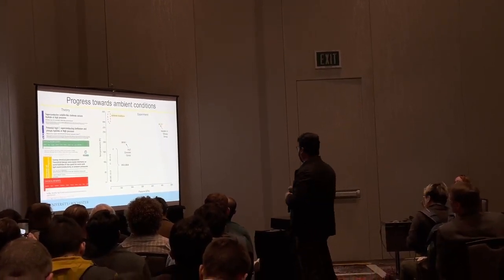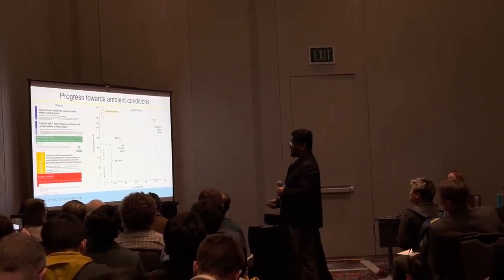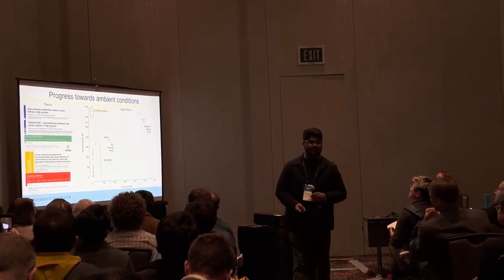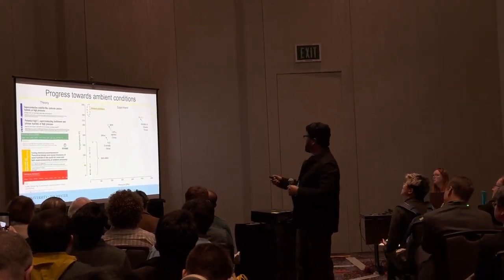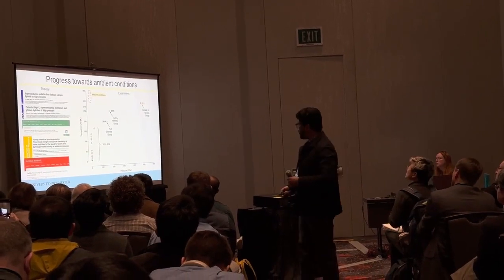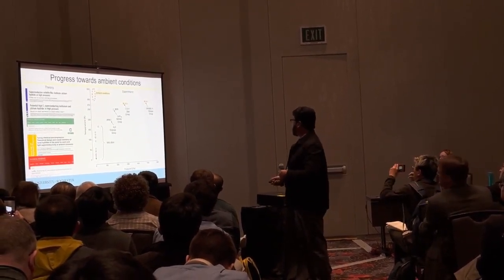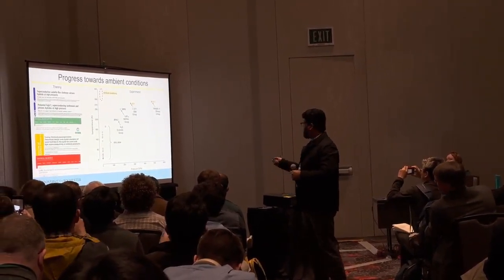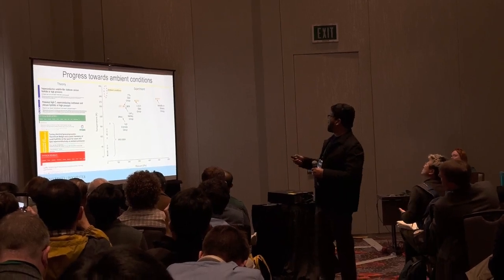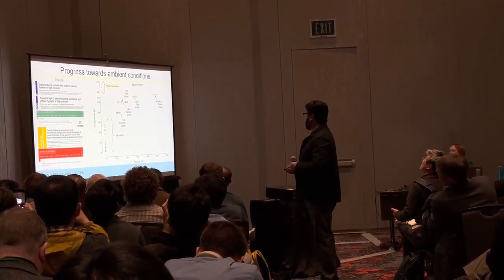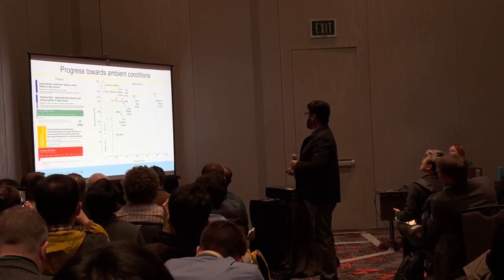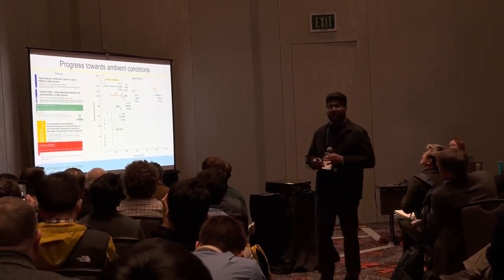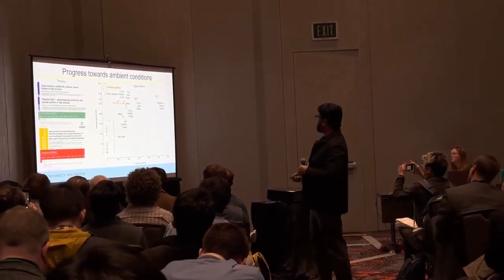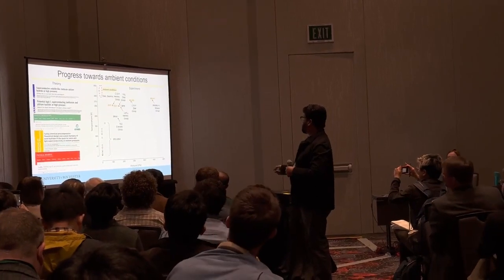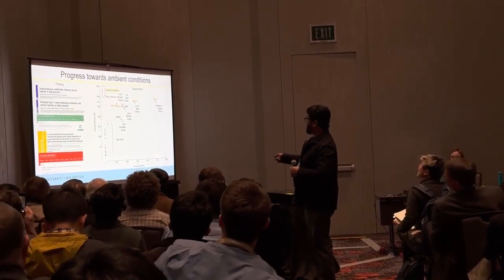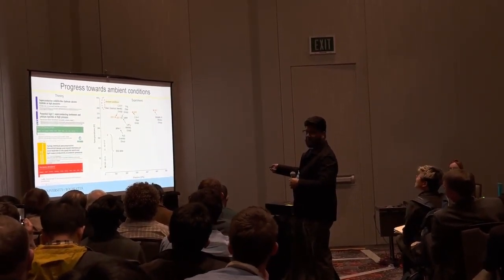So the first of that kind came in 2014 by Eremets' group for hydrogen sulfide. And in 2019, lanthanum hydride from Hemley's group. And in 2020, from our group, the carbonaceous sulfur hydride, reaching room temperature. And then in 2021, yttrium hydride. And then recently, again, carbonaceous sulfur hydride via carbon tuning. We were able to bring down the pressure from 100 GPa. So this is where we are. So the point that we want to get to is ambient condition right here.